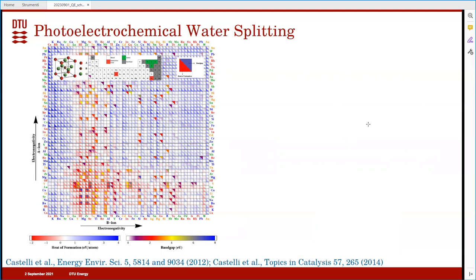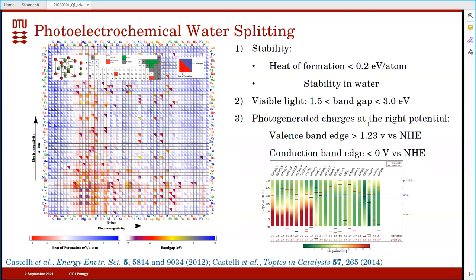And then you find out when you have red and red that the material is good. Then you can go beyond and also look at the position of the band edges, and you end up with about 20 different candidates that some of my colleagues tried in the lab. And some of these actually were found to work.